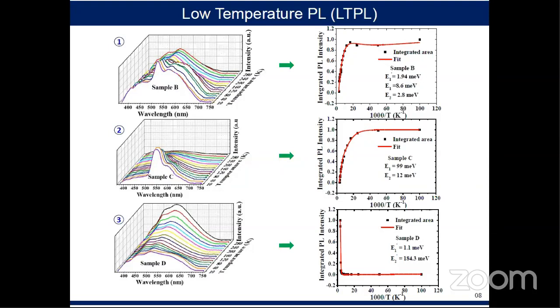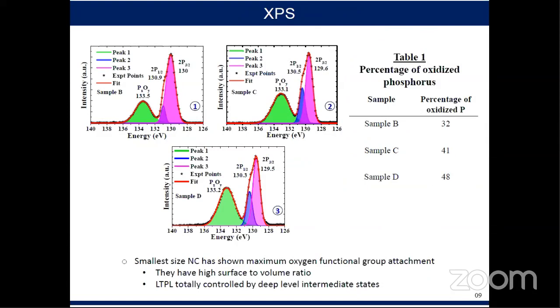Next slide. We have performed XPS measurements to know the chemical states of the phosphorus and oxygen groups. We can see that along with the phosphorus 2p doublets, there is another higher energy oxidized phosphorus band, PxOy. That is how I have represented it.